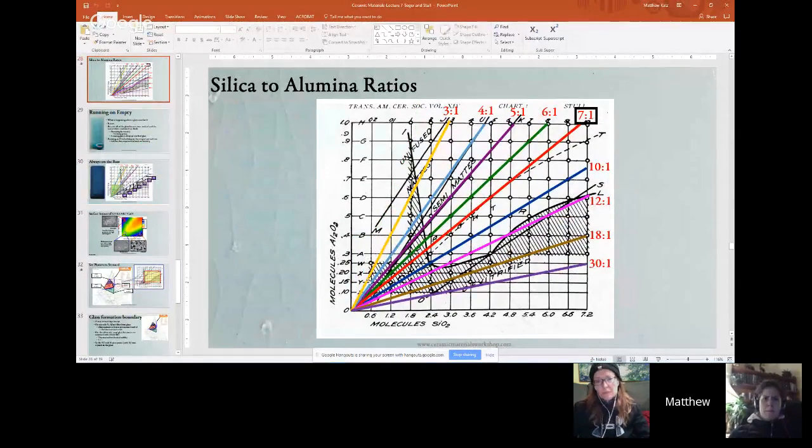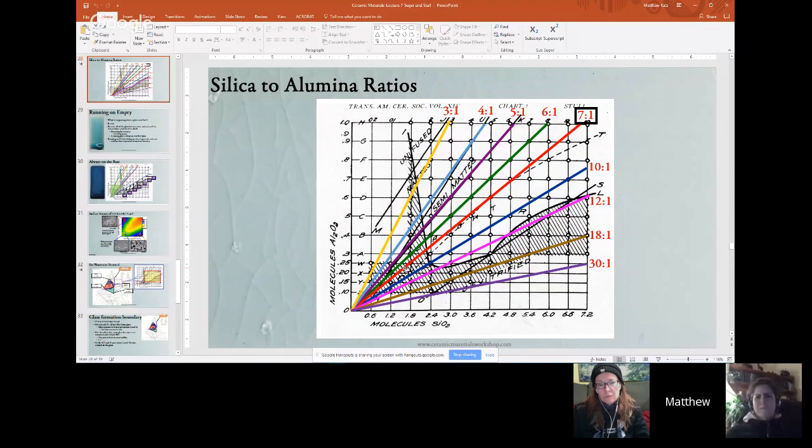When we're down in this lower region, the compositions just switch so easily back and forth. And you find a lot of glazes that are known as breaking glazes that will crystallize when they roll over an edge, that sort of thing. That's really taking advantage of that phase separation, where it totally looks like a completely different glaze. A lot of that is manipulating the running along with manipulating the chemistry.